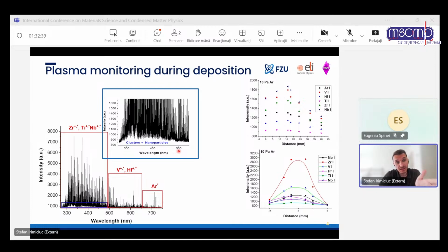But the main difference here, if you remember the magnetron sputtering deposition, is the ratio between the lines. In the magnetron sputtering case, the argon lines were dominant, and you could see really low lines of zirconium and all the elements with a lower ionization state than what we have here. Here we see it more dominant. So this also gives us a fact that the plasma is more energetic, and a more energetic plasma could